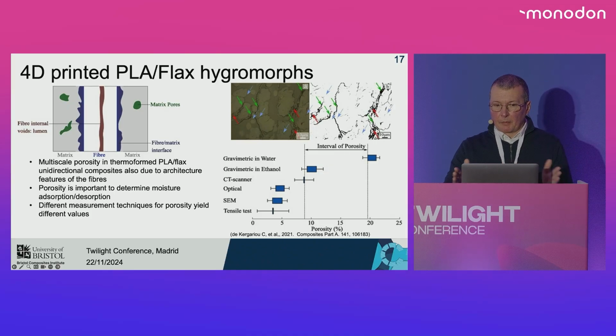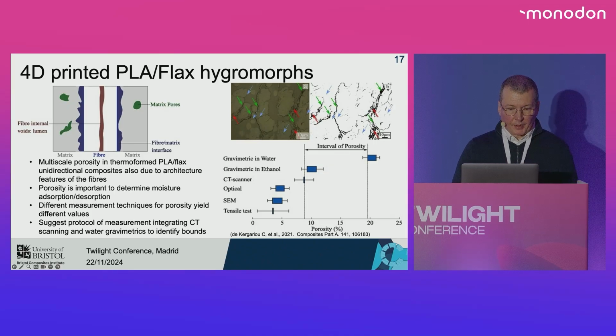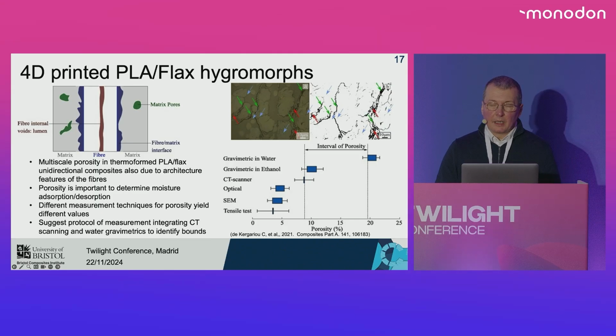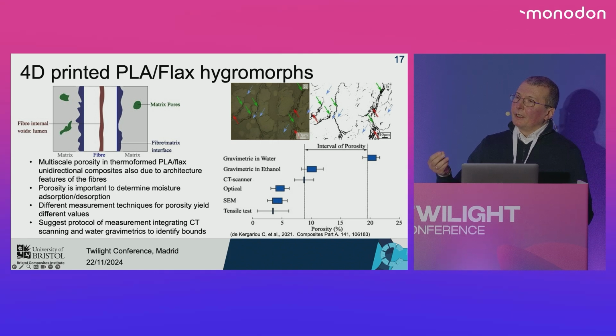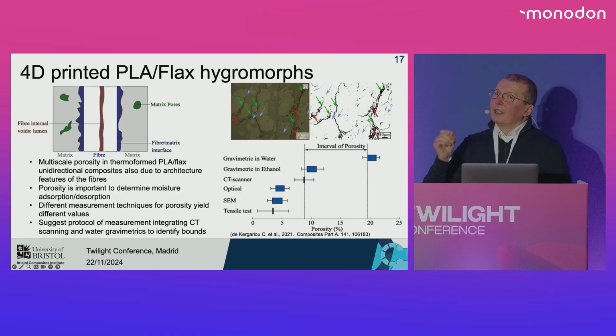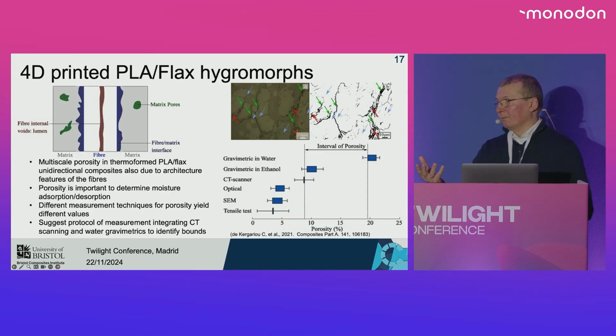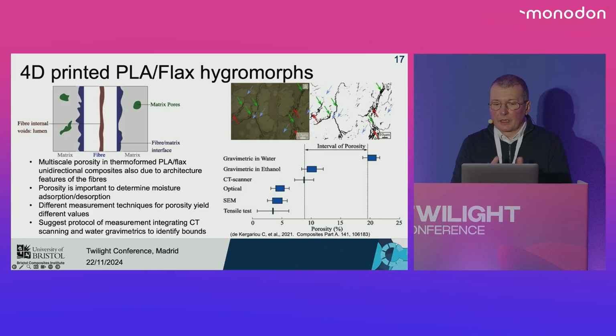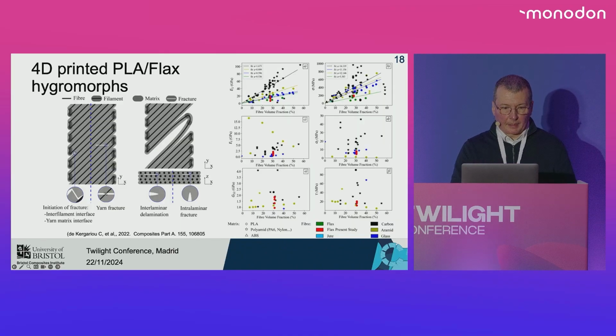So we made by thermoforming several PLA and flax composites. And in essence, if you really want to have a good indication of the effective porosity in these types of natural fiber composite, you will need to integrate computational tomography scanning and water gravimetrics to identify bounds. And if you don't have access to CT scanning, carrying out gravimetric testing in ethanol is probably a better option, because we have seen that they are slightly closer to the CT scanning.